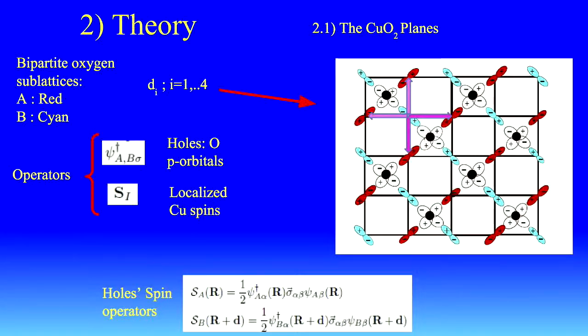And nearby is the copper oxide. So the actors are the localized spins, because these copper ions have localized spin one half. And as we dope the system, we introduce holes in these oxygen p orbitals, either px or py. And by the way, these are the expressions for the spins of the holes in the A and B sublattices. It's a bipartite square lattice.